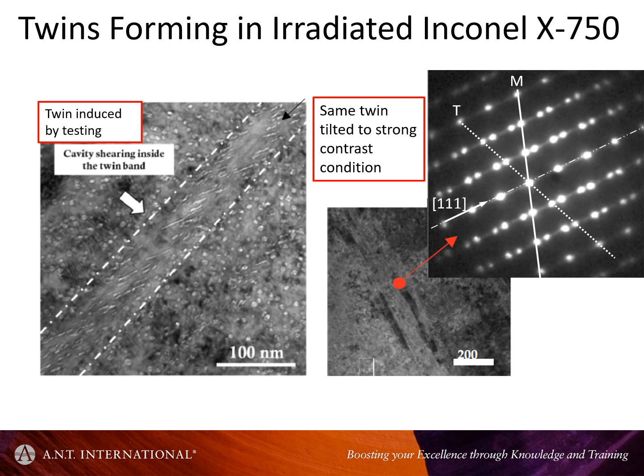In the last 10 years, I guess there's been a lot more exposure to bubbles, small cavities in neutron irradiated materials at low temperatures, whether it's steels or in this particular case, Inconel X750 from the Candu reactor. Oh, actually, this isn't from the Candu reactor. This is a proton irradiation. Excuse me, this is a helium ion implantation followed by deformation. This is some work done at Queen's, and I see I've left off the reference here. I'll have to put that in the reference slide.